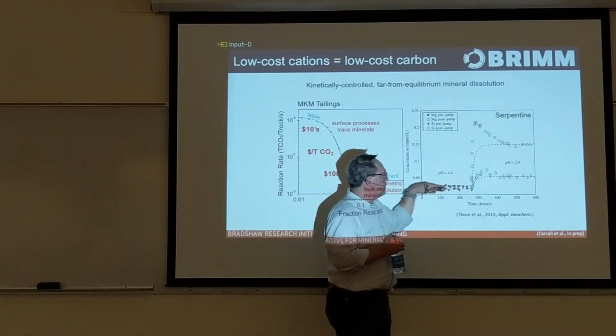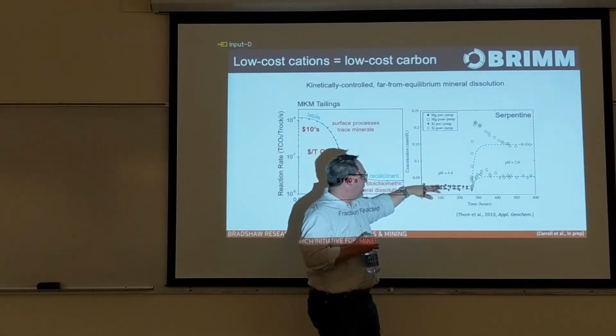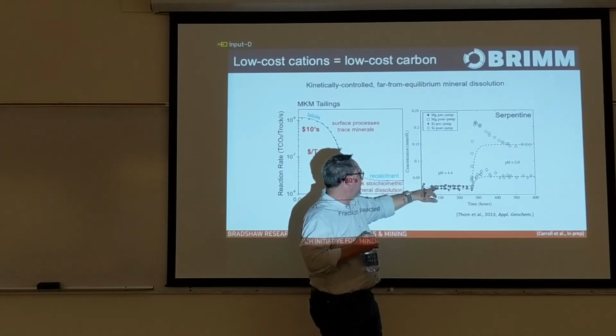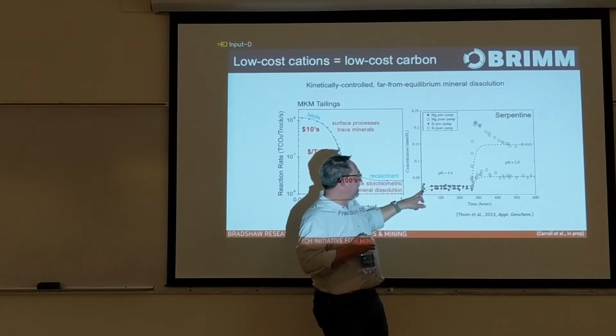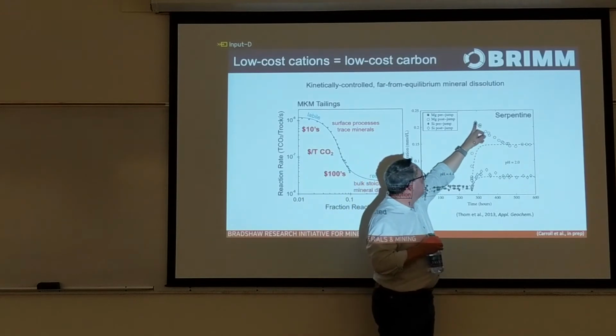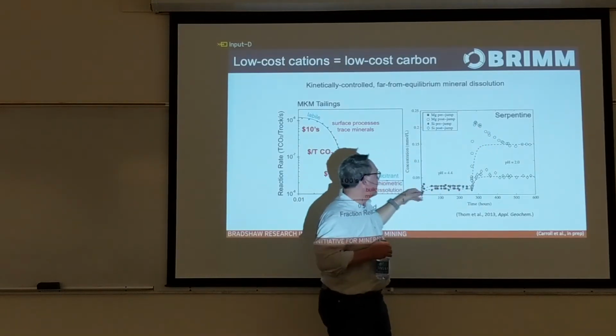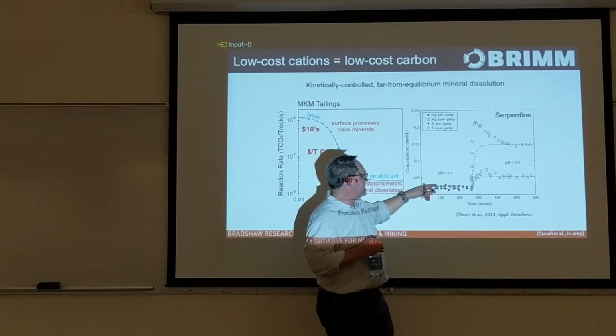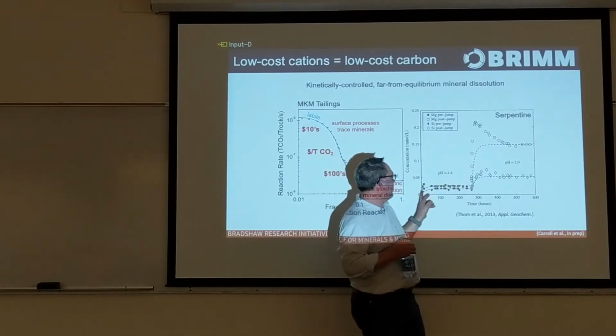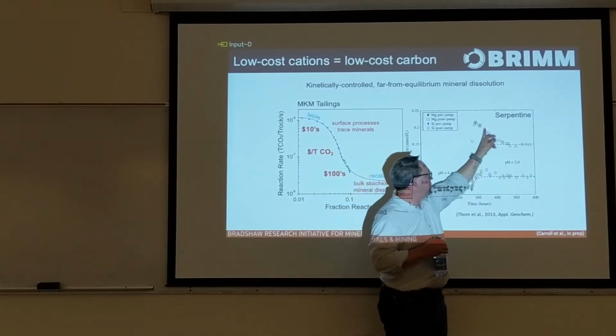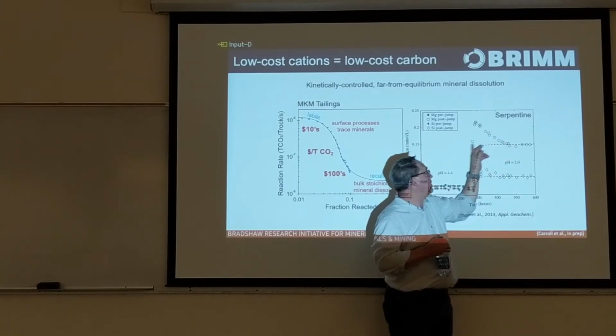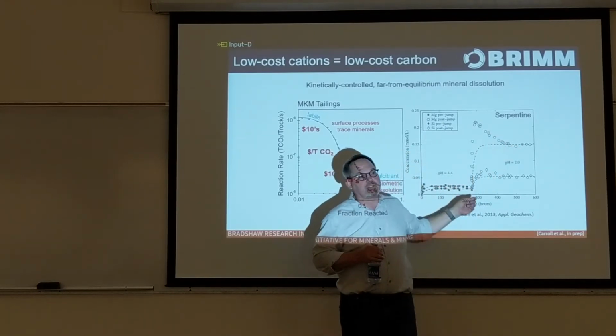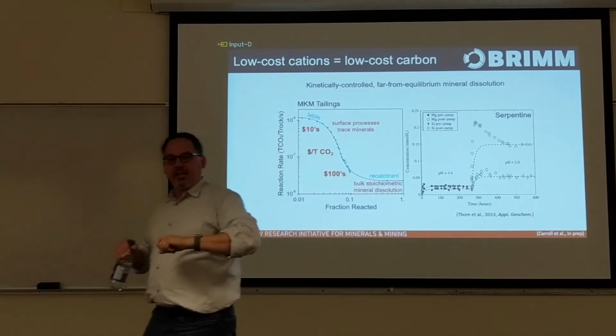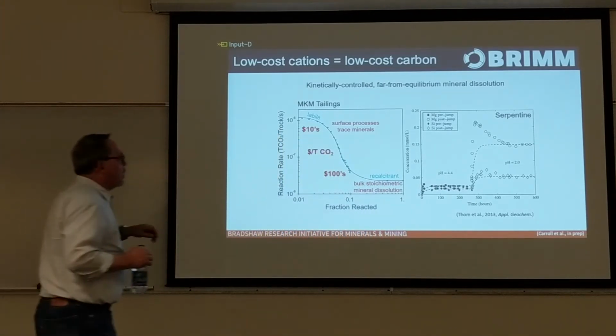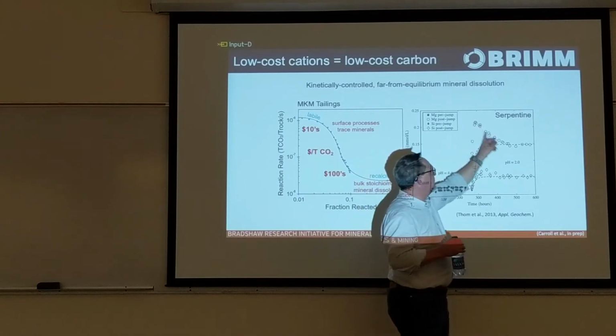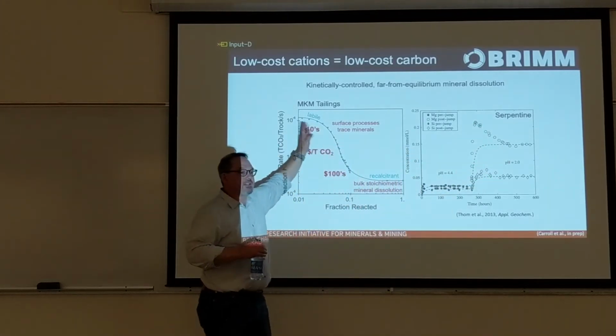And you can see that if we do pH jump experiments. So this is part of James Thom's work that he did towards his PhD. We essentially are looking at magnesium concentrations in a flow-through reactor. Starting at one pH, if we go through a pH jump, we see a transient. We do another pH jump, we get another transient in magnesium. This is in the same material running continuously. So after several hundred hours of reaction, if we just change the inlet pH, we get a transient increase in magnesium release that's equivalent to this fast release.